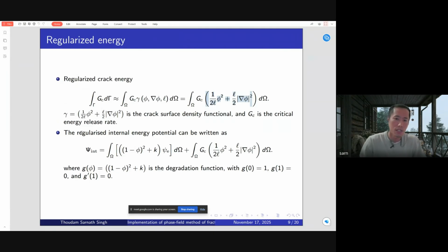Since we have defined the crack as a density, we can now convert this surface integral to a volume integral. When we convert this integral into a volume integral, we don't have to track the crack surface area, so we don't need to know the crack surface area. Because of this conversion from surface integral to volume integral, the numerical implementation is easier. And also when we are dealing with very complex cracks, this formulation is much easier to deal with. We call this the regularized energy of the system.